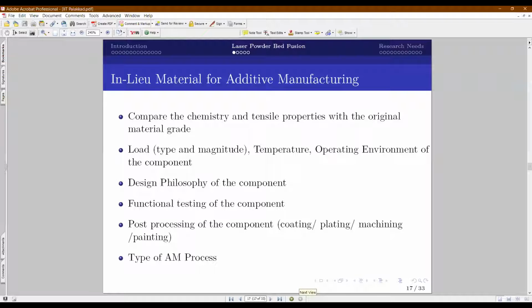Next, we look at 3 aspects of the functionality of the component. What is the load acting on the component, and what magnitude? What is the temperature of exposure? What is the operating environment, especially a corrosive environment? So in the first phase, I have identified a particular 3D printing equivalent grade. Now, based on this data, especially for fatigue loaded components, we look at what temperature it is exposed to, the operating condition, and what the load is. Then we try to understand in these aspects whether this equivalent grade is okay or not.